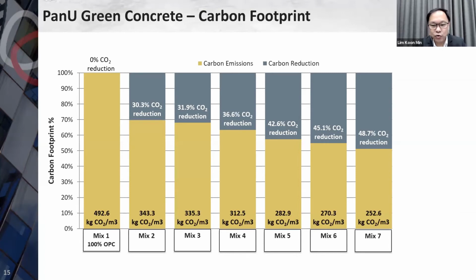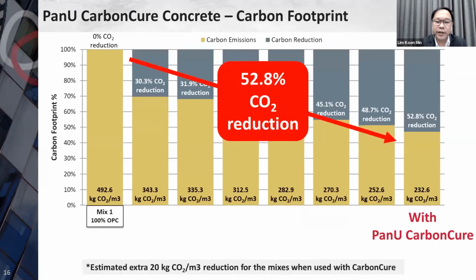Now, when we introduce this CarbonCure concrete, we are able to achieve a breakthrough of more than half, which is 52.8% to be exact, of CO2 reduction. So whatever recycled materials we use to replace, and we put in CarbonCure concrete and the CO2, we are able to further reduce the cement in the concrete.